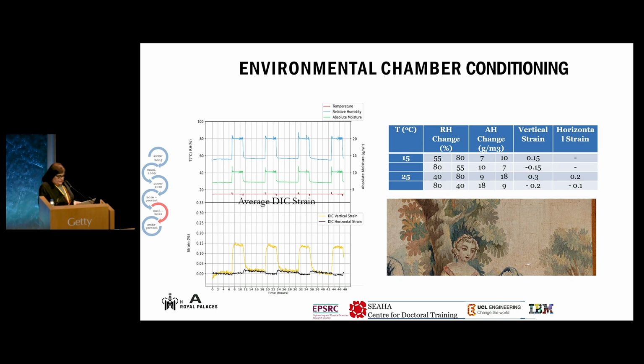In the vertical strain, increases of approximately 0.15% were observed in all cycles when RH changed from 55 to 80. Changes of almost the same magnitude, but with a negative sign, were observed when we had the change back to 55.